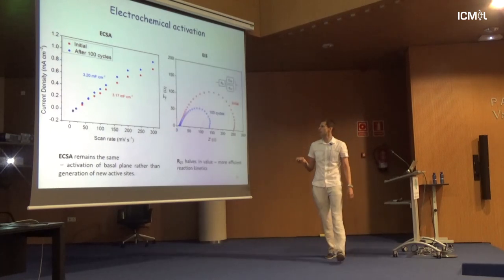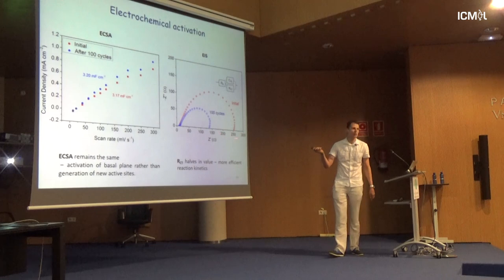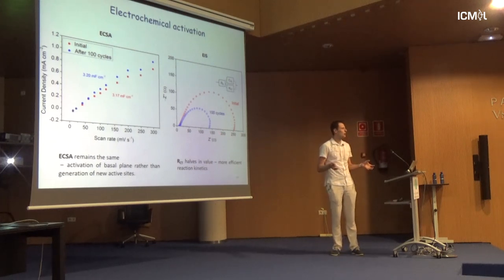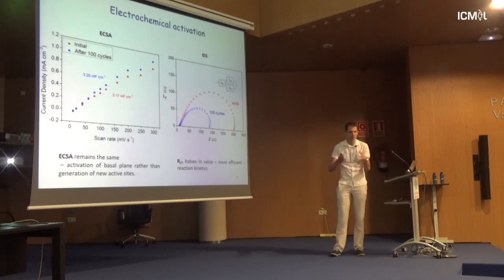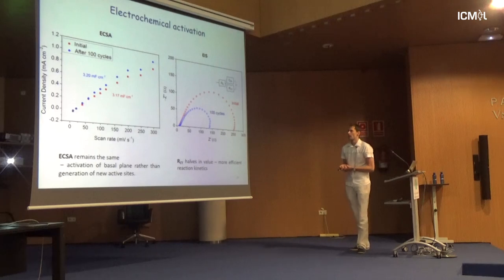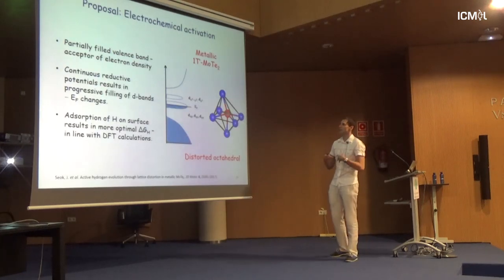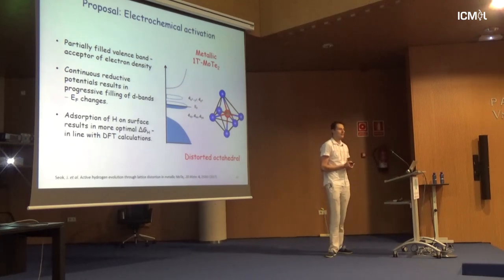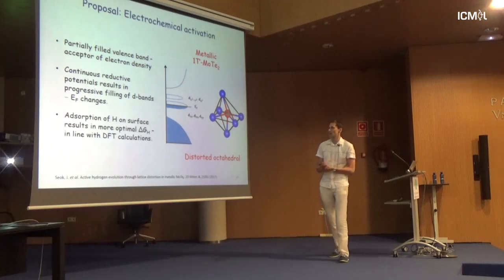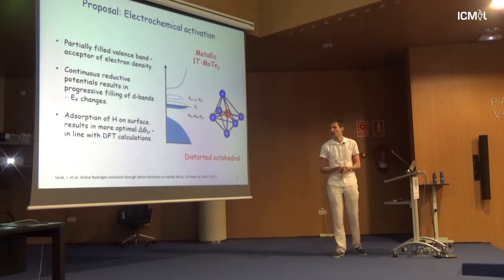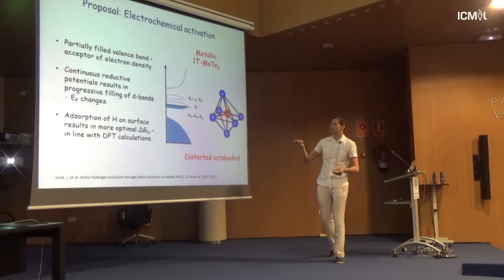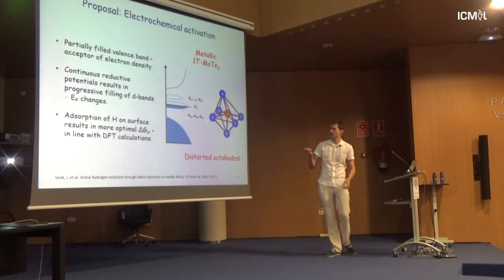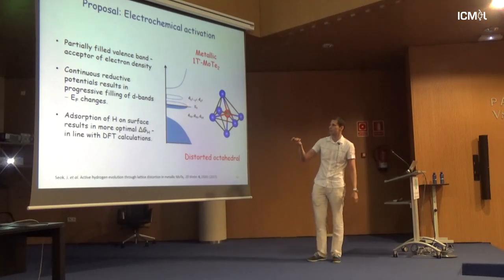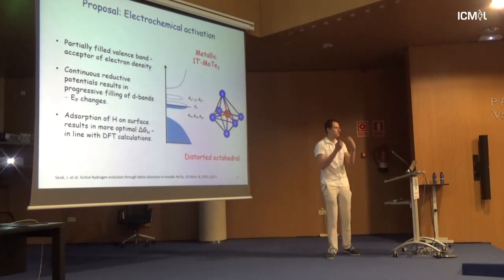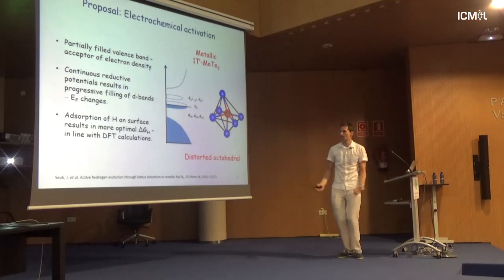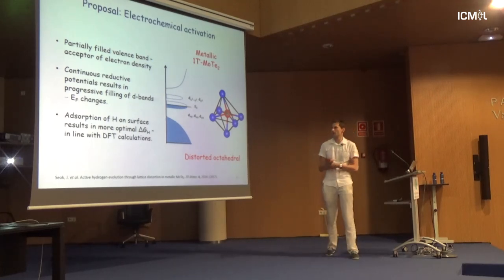The only thing that changed is the impedance spectroscopy. So it's getting a little bit more conductive. Or we can claim it's getting more conductive. So you have an easier charge transfer towards your surface. So after thinking about it, we came up with the electrochemical activation idea. So we look at this very primitive band structure, it's all calculated, but it's just this very nice cartoon. And what it did, we have a half-filled band, and that means this material can accumulate more electrons. So once we pump in these electrons effectively into our material, we change it.